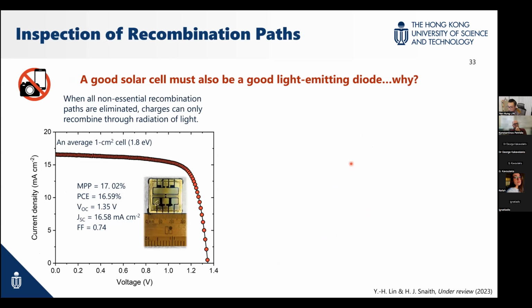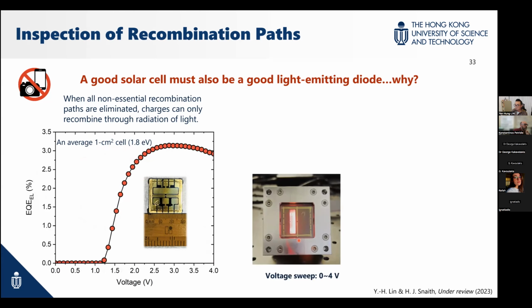Okay, there is a saying about perovskite solar cells: if we have a good solar cell, we're supposed to have a good light-emitting diode. So we actually took a very mediocre cell. You can see here it's only 16.6%, but it's a 1.8 eV cell. It's actually not too bad. The highest one is below 0.1 square centimeter and around 20% nowadays. So this one is 1 square centimeter, a large cell, and you can see that the JV curve is not so perfect. But we use this solar cell even though it's not optimized for light-emitting diode structures.